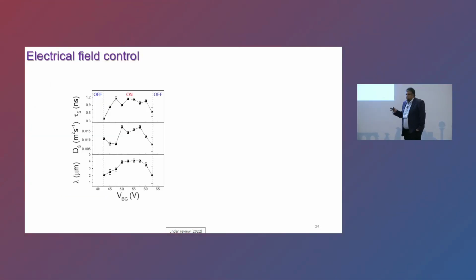As I mentioned, one of the challenges that we were seeing with graphene spin valves is that you really cannot do any gate voltage dependency because it's a semi-metal. You cannot really turn on and off the charge current propagation much. But in the case of black phosphorus, it's a semiconductor. And what we have seen is that you can really turn on, and then again turn off, spin propagation by just applying a gate voltage. The first part is just coming from the fact that the material is insulating at this gate voltage regime.